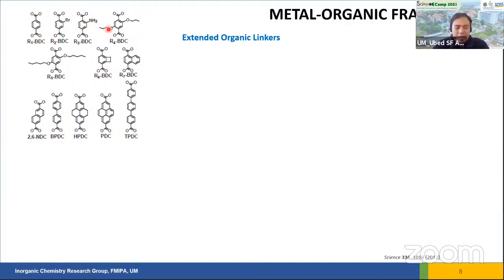So we can modify the organic ligands to make a beautiful structure and for specific application. Another direction is also to elongate the organic ligands. For example, if we use terephthalic acid, we only have one benzene ring. If we use biphenyl dicarboxylic acid, we use 2 phenyl rings, meaning the structure will be bigger in pore size. And on the other side, if we use 3 phenyl rings, like this one, the MOF structure will also have a bigger pore size.